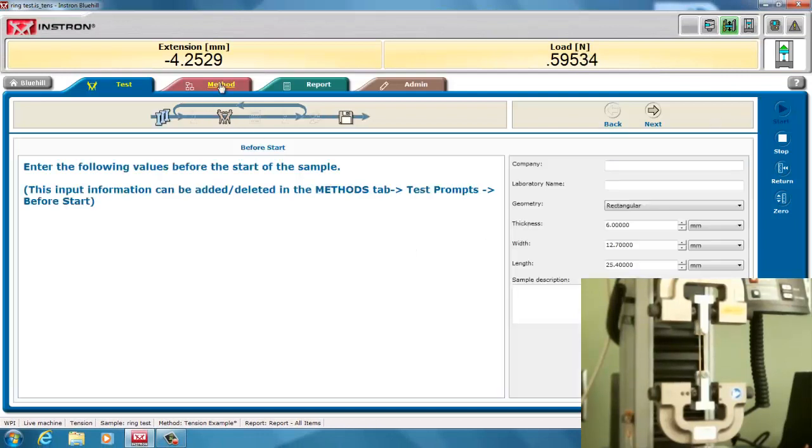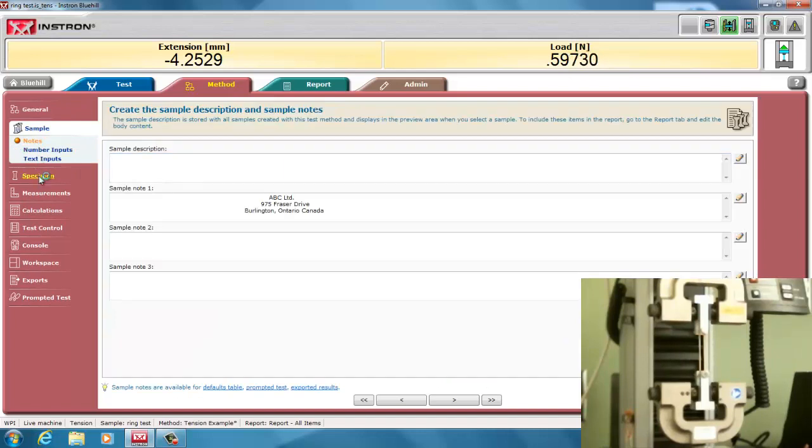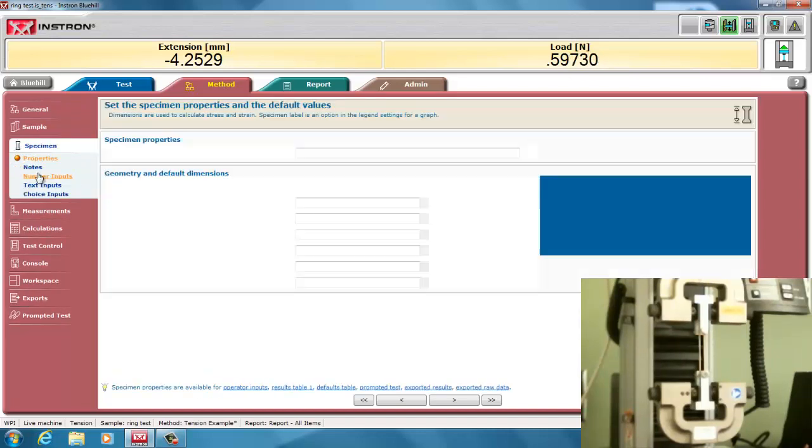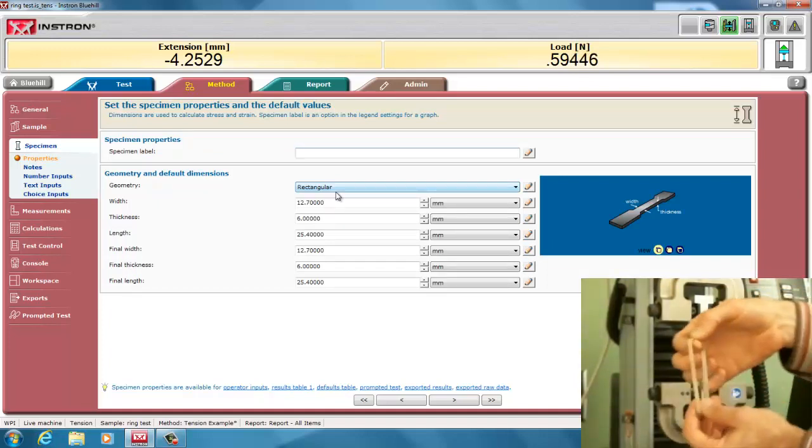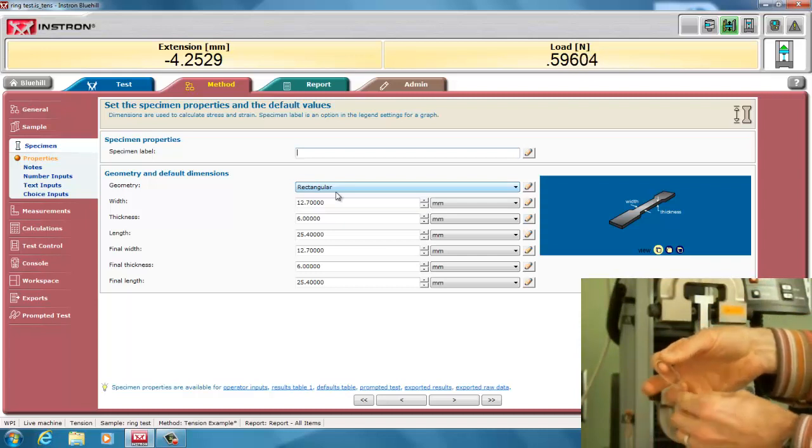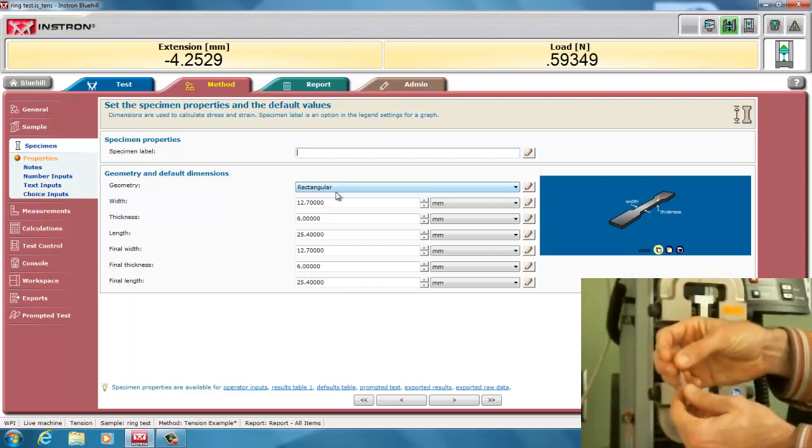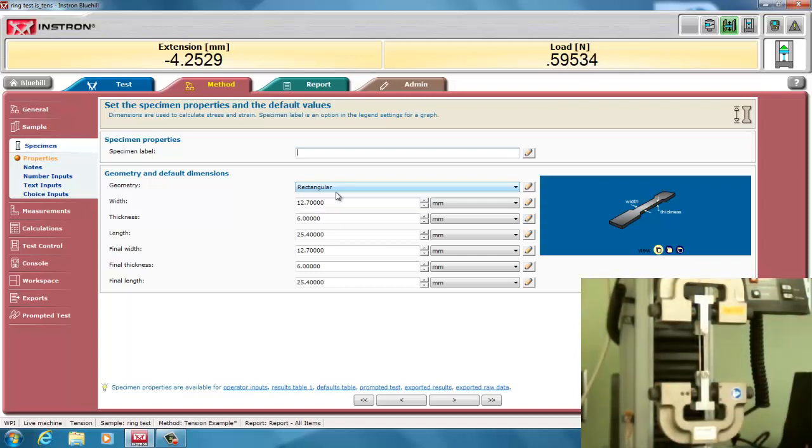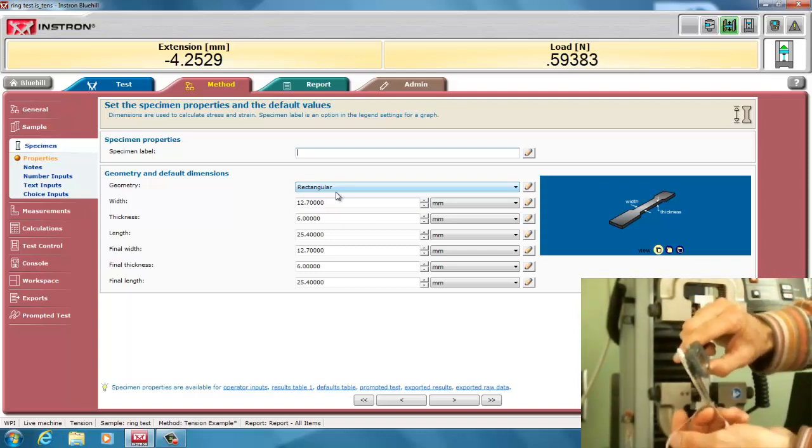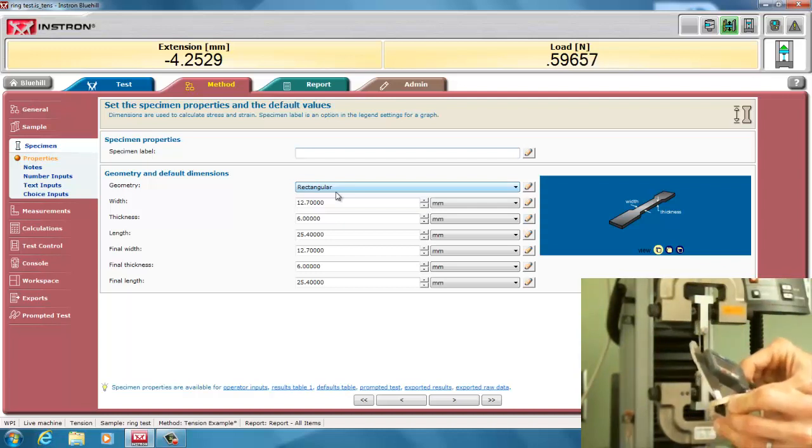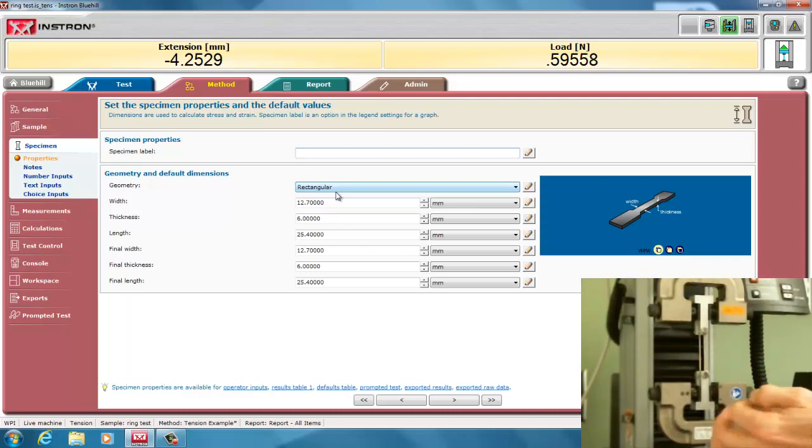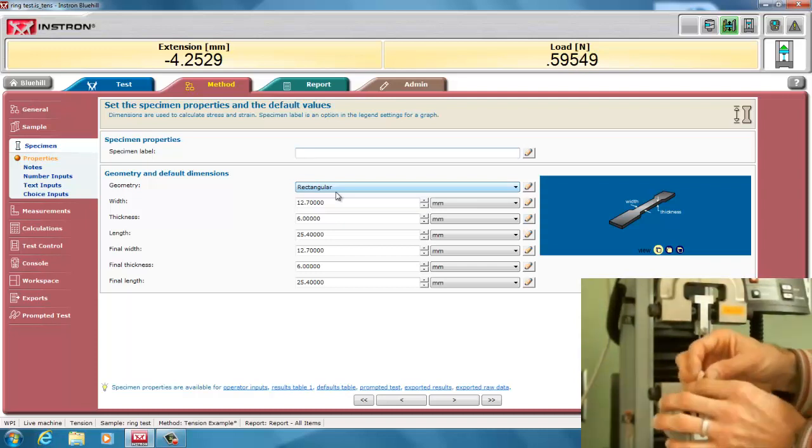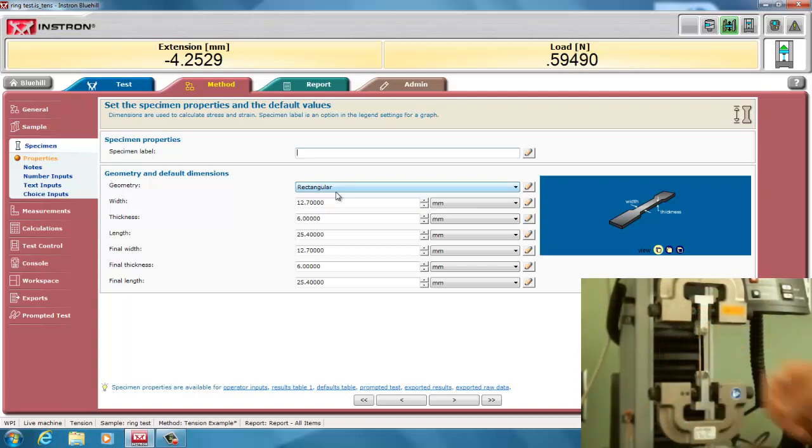In this method, we have the specimen is rectangular, but as you notice, for a rubber band, we have two sides, so if we want the stress calculations to be correct for this sample, we need to measure the width and the thickness of this sample and multiply times 2. So I would suggest multiplying using a width value that you get from the sample and then multiplying the thickness by 2.